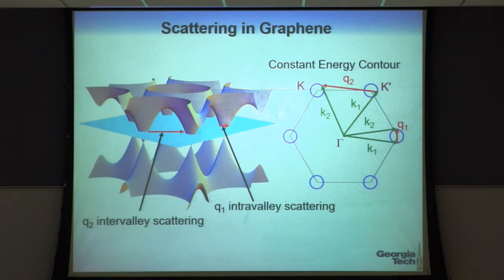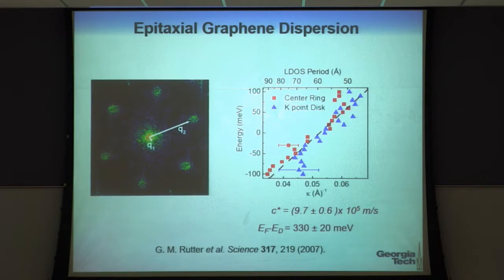And if I take a Fourier transform of the data that I showed you as images, as XY images, the Fourier transform might look something like this. It does look something like this. It is that. And if you do that at many different energies, you can get out the Q vectors, or the K vectors, if I sort of just multiply by 2, if you look at the previous thing. And you see this line. That line, in fact, is the edge of the Dirac cone.